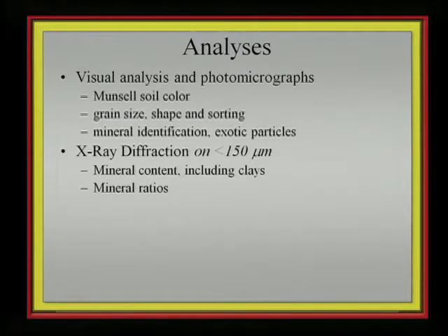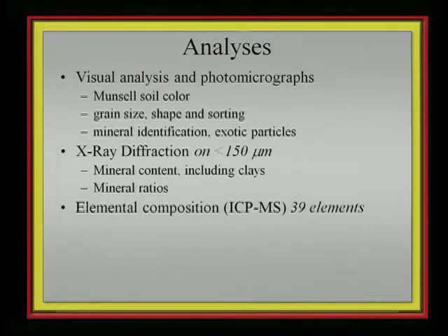There was quite a bit of clay content, and the identification of clays under PLM is rather difficult, so I did X-ray diffraction. I also wanted to get a more quantitative definition of what the ratio of different minerals was. And then I also did elemental composition by solution ICPMS.